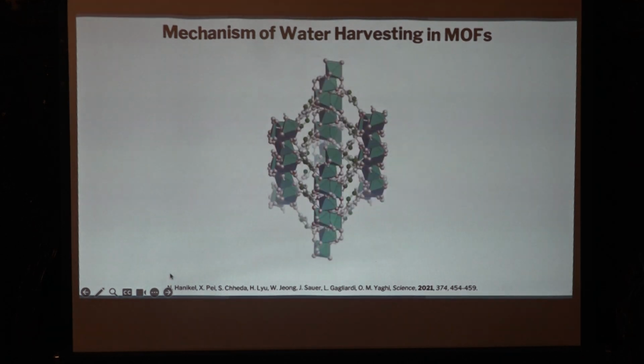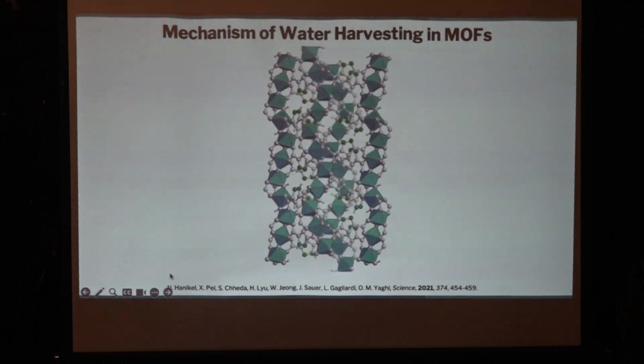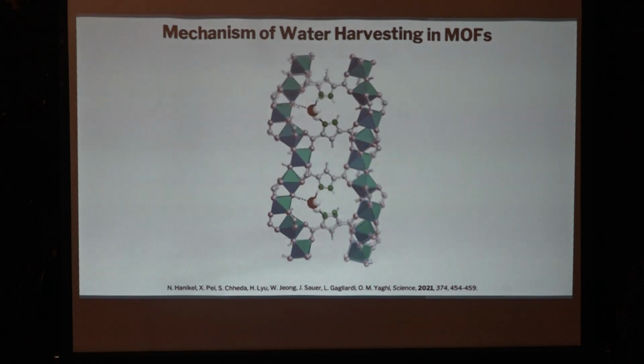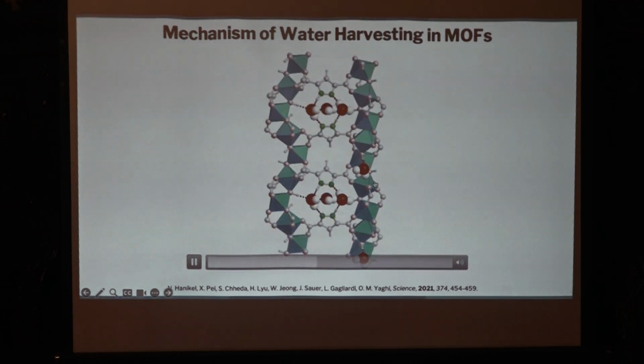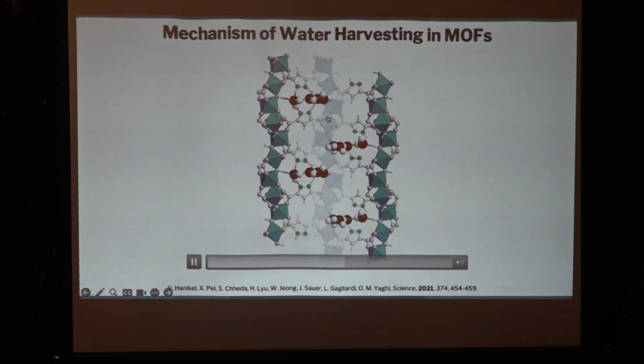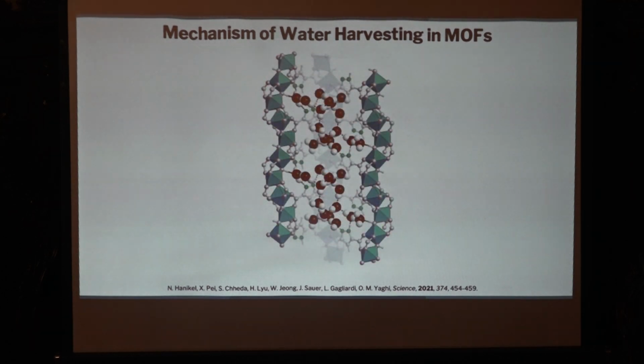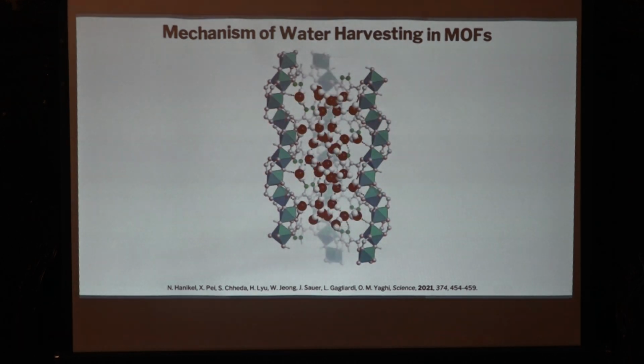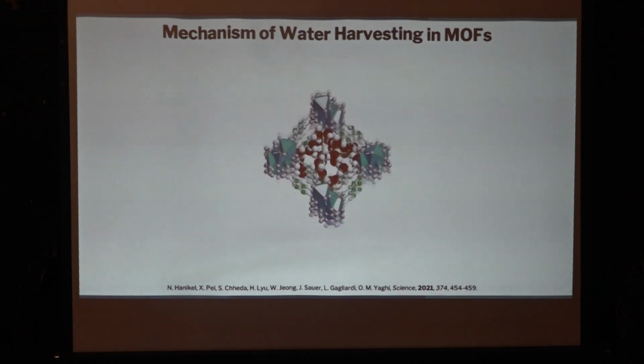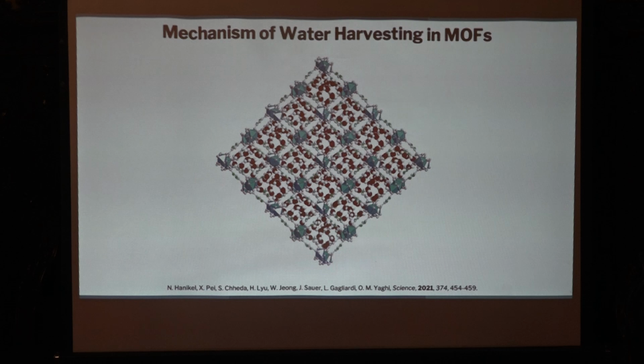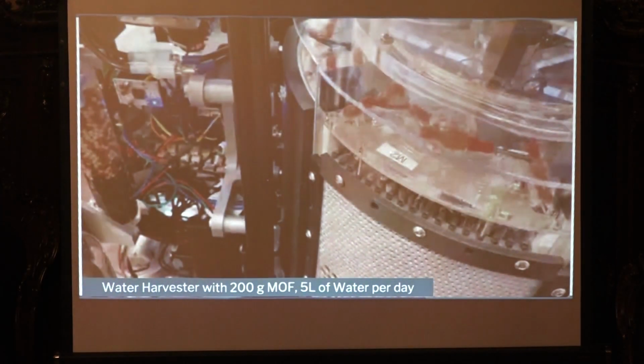Let it play now. You'll see the water molecules going to the hydrophilic sites, and then when the hydrophilic sites are saturated, you bridge over the hydrophobic sites. The hydrophobic sites repel water, while the hydrophilic sites attract water. This repulsion and attraction allows you to modulate the strength of water binding, and therefore modulate the temperature at which you can release the water. So the water can be released from the system at less than 50 degrees Celsius because of that push-pull attraction, repulsion interaction. Again, it took many years, and now we have a machine that deploys that MOF.